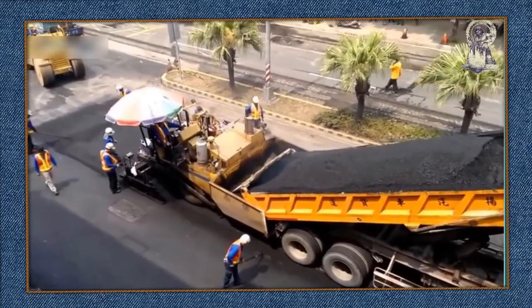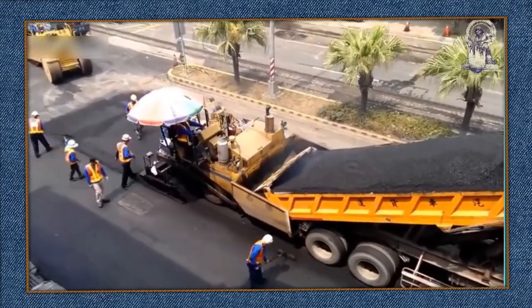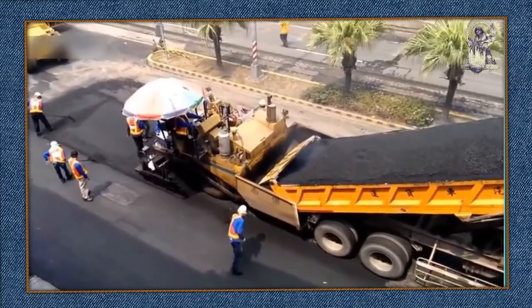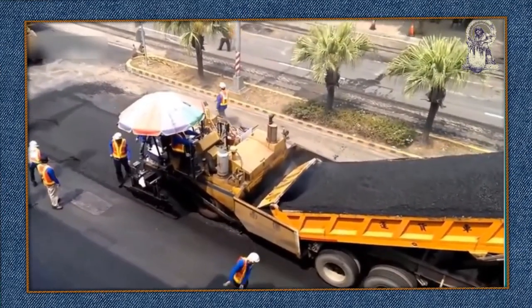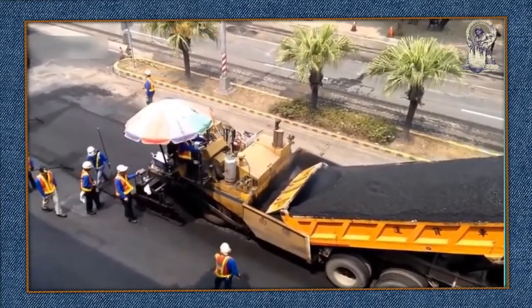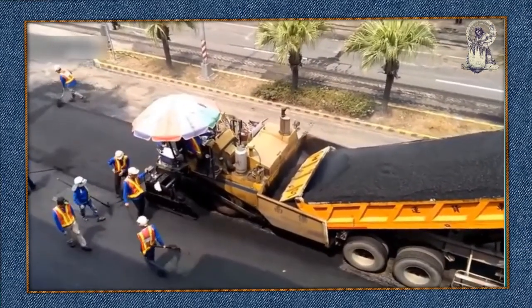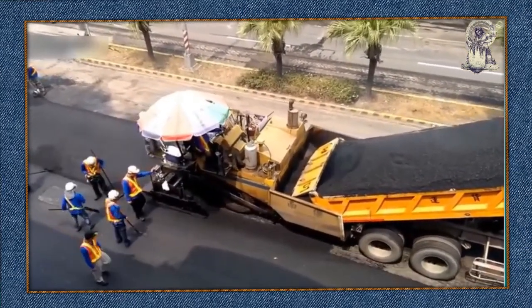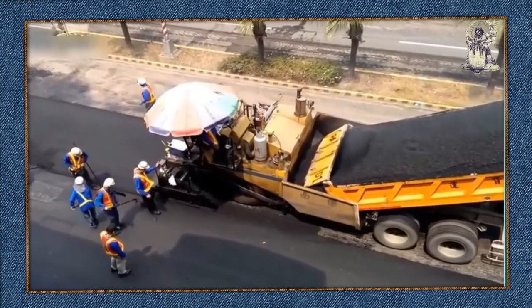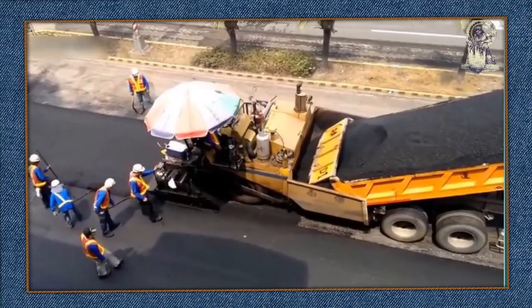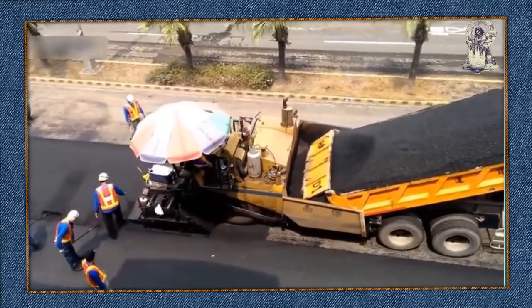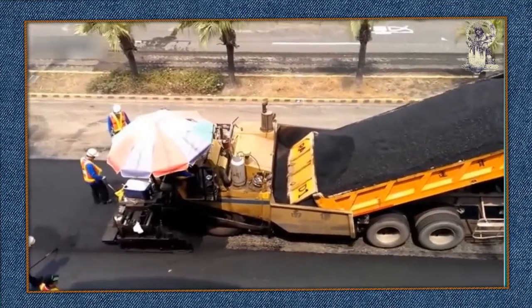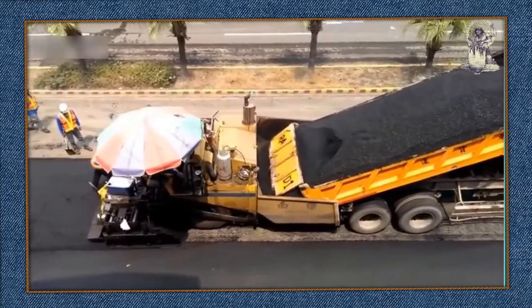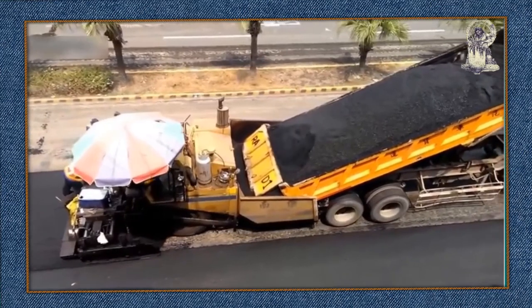There are different types of pavers available. 1. Simple mechanical paver. 2. Fully automatic paver, which is controlled by sensors. 3. Fully computerized paver. The laying temperature of the asphalt mix is 120 plus or minus 5 degrees. The asphalt mix is laid through pavers at laying temperature, and it is compacted up to 98% of compaction through vibratory rollers and pneumatic rollers.